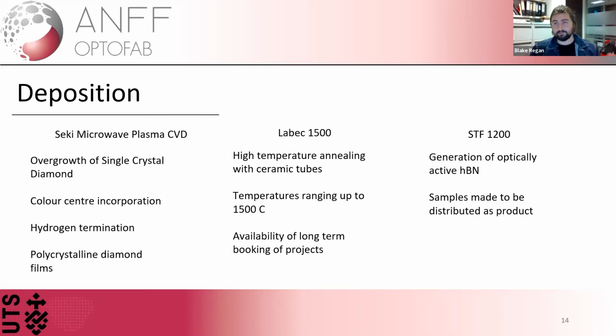Beyond the growth of simply diamond, a number of users have actually started using the Seki Microwave Plasma CVD as a hydrogen termination tool, where predominantly it's being used just with other non-diamond samples. And because in all my scientific training, I'd had ample access to this CVD reactor, I wasn't aware how difficult it was to get your hands on a high power hydrogen plasma. So a lot of users have actually come in with the simple desire of putting a hydrogen terminated layer on the outside of their sample for whatever erroneous process they have.